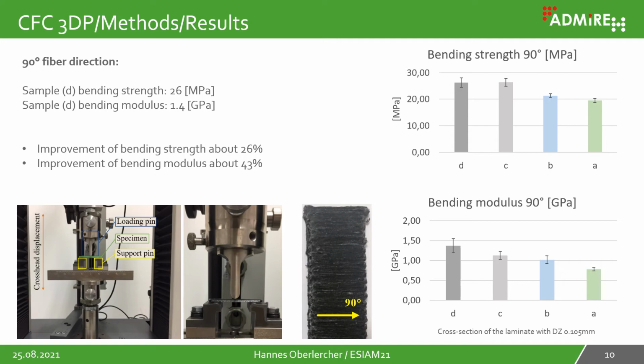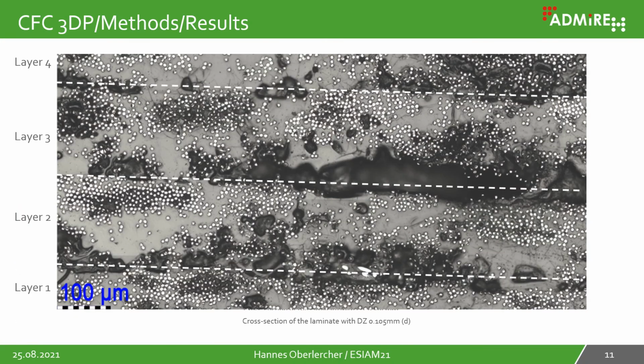An improvement from A to D in the strength of about 26%, and in the modulus also from A to D about 43%. We also made a microscopic cross-section of sample D. It showed us the same picture as Markforged delivered, a high content of imperfections, which is an indication of insufficient heat transfer into the material, and this still reduced the mechanical properties.